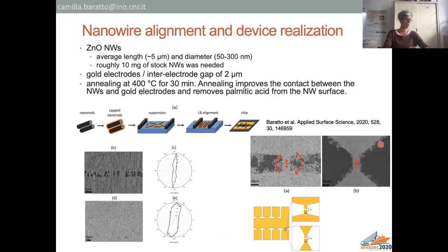In this collaboration we took advantage of the experience of the Tampere group on Langmuir-Blodgett, and we used this technique to align nanowires between two contacts. So basically we selected zinc oxide nanorods, we coated them with some chemicals to let them float over water surface in the Langmuir-Blodgett trough. And then the barriers were put one near to the other, and this allowed the alignment of the nanowires on the surface, just like trunks in a river. And then we put the chip to collect the nanowires, and the chip has already deposited the contacts.